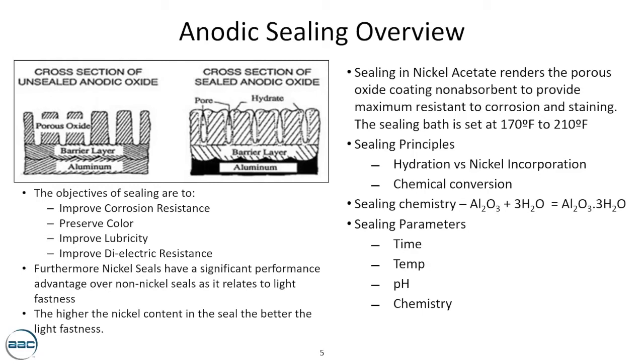And that lubricity comes from a specific surfactant used in your nickel seal. And then improve dielectric resistance. So as I mentioned earlier, the sealing step is vital for a number of reasons, and that just hints to some of it. And as we go through this process, we'll understand there's an interplay between how we get as much nickel in the coating as possible, but also hydrating it at the same time, because you need both elements in order to ensure a good seal. You need some sort of UV filter, in this case nickel, but that needs to be accompanied by a hydration step.